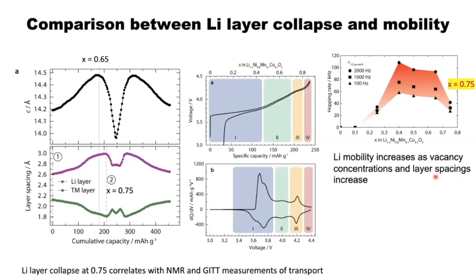So let's go back and look at the diffraction data and try and pull it all together. So remember, I said that the C parameter collapses at 0.65. So that's not where we see the decrease in the lithium mobility. We see the decrease in the lithium mobility rather at 0.75, but if you unpick the different layer spacings of the transition metal layer versus the lithium layers, you see that's where the lithium layer starts to collapse and increases the activation barrier for transport and the lithium mobility decreases.